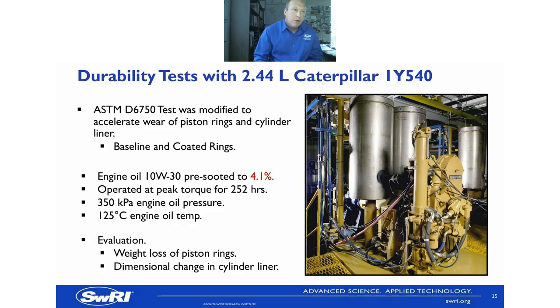It's not really the focus of this presentation, but we ran it with a 4.1% soot. And therefore, obviously, if it's running with pre-soot lubricant, that's higher wear oil than you'd experience if it was brand new. We did 252 hours at 350 kilopascals, so basically high pressure and relatively high engine temperature.